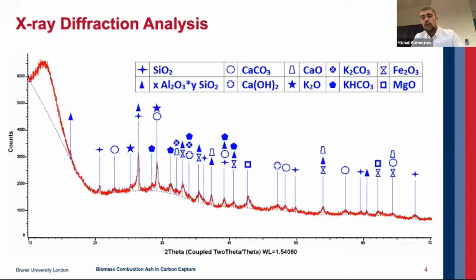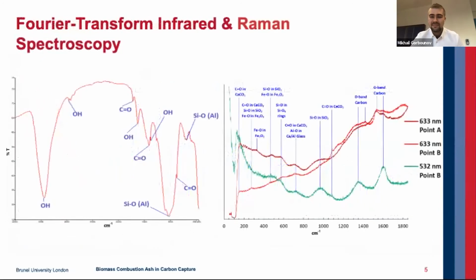It should also be noted that we can see ferric oxide, Fe2O3, but it is perhaps more suited for carbon monoxide chemisorption rather than carbon dioxide, because upon contact with CO, the reduction process starts to occur. So it goes from Fe2O3 to Fe3O4 to FeO, and then finally to pure iron. And during this reaction, CO2 is actually emitted as a byproduct. But this compound can be very helpful for decarbonizing the steel industry, but that's a different topic.